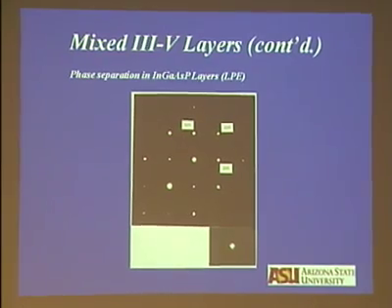When phase separation occurs, you produce satellite intensity, and the reason is that the indium-rich regions have a larger lattice parameter than the gallium-rich regions, which I'll argue in the next slide. So there is phase separation in these materials, and summing it up,